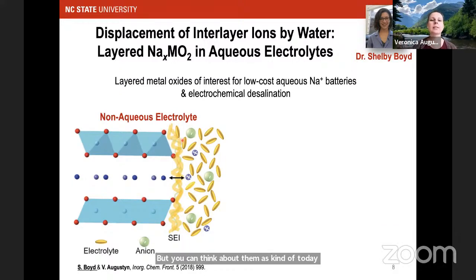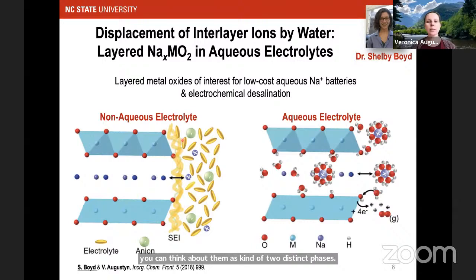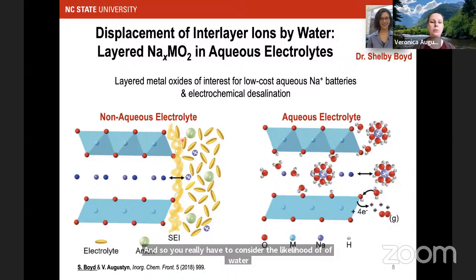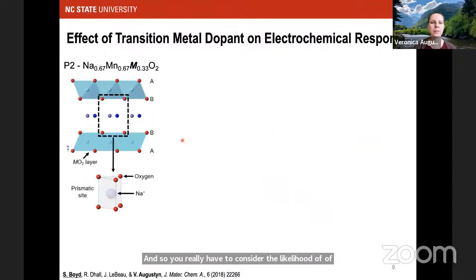distinct phases. On the other hand, in aqueous electrolytes, you don't have this separation oftentimes. Water has a tendency to penetrate into your material. You don't have a solid degradation layer from your electrolyte. And so you really have to consider the likelihood of water infiltrating into a layered space, for example.